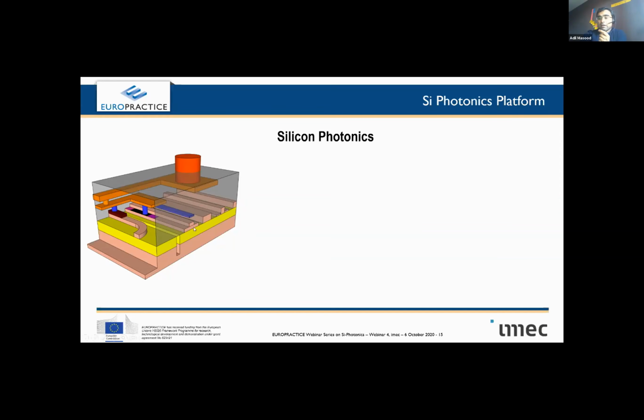And now, at least the technology we offer for silicon nitride, we do not do much with silicon nitride in terms of doping or chemically changing it at all. But with silicon, doping has been happening since the very first chip was made, probably. So you can see that this silicon has been doped, like this colored part shows the doping layer. It can also be silicided, which means partially made into sort of a metal, which is for contacting, as shown in these vias.